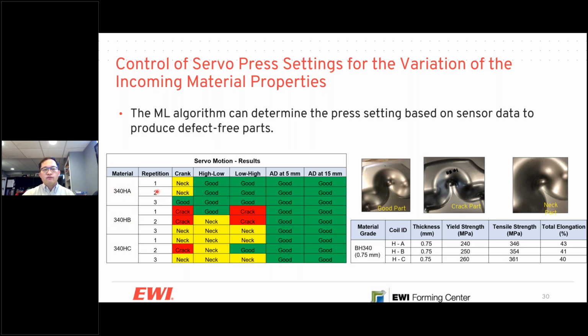And then we found that we actually implement the 5 different press settings, and you can see that based on the incoming material property variation, we actually get different quality results. For instance, with that crank motion, we have only one good part out of 9 tried. But when you're using a different cushion control system or different press motion control, we actually have 100% good parts for this specific 340 material by implementing this control algorithm.